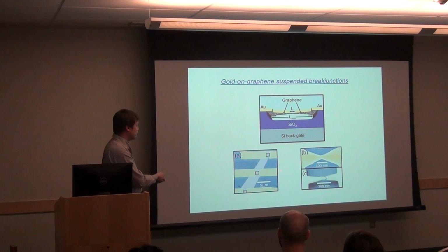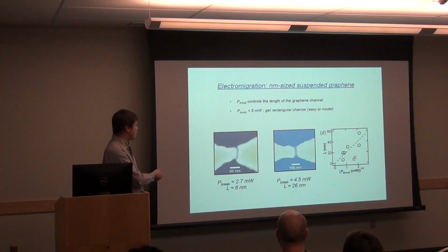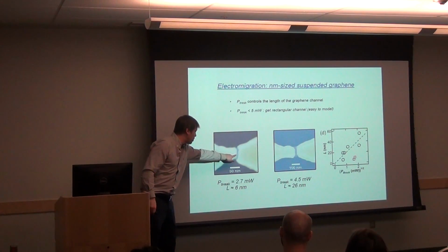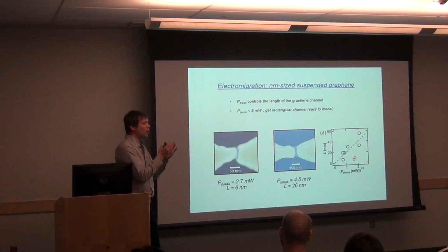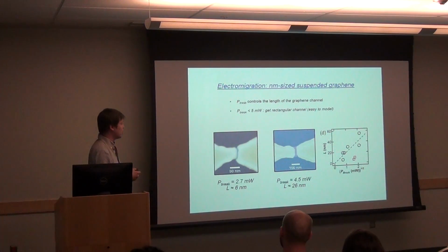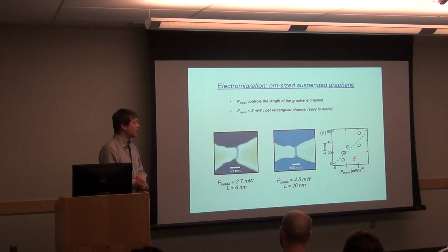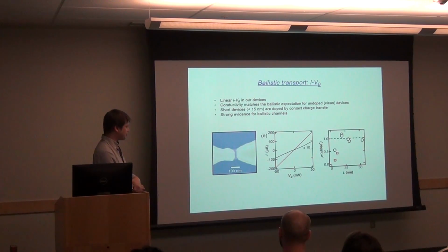We also do the same thing with graphene now. So in graphene, we can also make very small devices. We suspend them, in the case they're bow tie shaped, and we electromigrate them again. And it makes a very short channel. This one is about 6 nanometers long. We can make them a bit longer, and we control the length with the power at which we break the device. When they're very short, one issue is that you are actually doping the channel with the contacts, so you don't have as much tunability in the device. But as soon as you exceed about 20 nanometers, you have a lot of tunability, and it turns out that they're great to map out the Hamiltonians we're interested in.